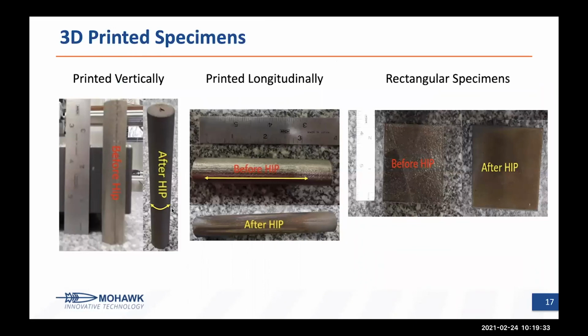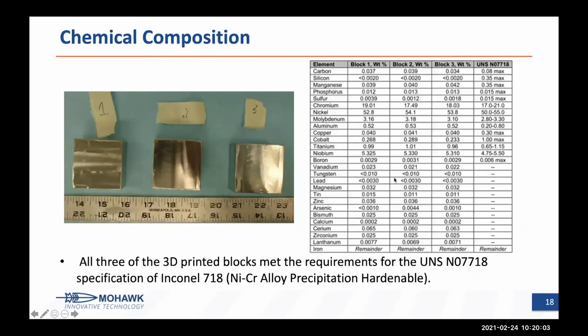The first one was printed up vertically. Just as you see it standing there, that's the way it was built up. And then the printed longitudinally component, which is laid here on the granite table. You can see it was built in this way in that direction. So if directionality, isotropy or anisotropy would be evident, we should hopefully see that in our tensile specimens. And then we had some standard blocks made so that we could do some other evaluations of the material.